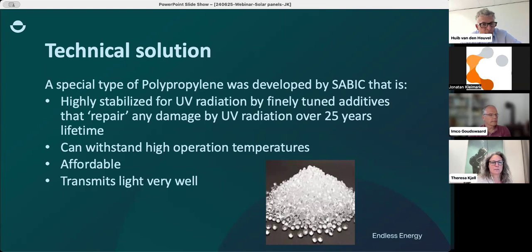So it can be used at quite a high temperature range. In our climate tests, we test them from -40 to 100 degrees. High UV radiation, impact, it's very good at impact, and it's completely non-corrosive. So for example, in salty water or with other aggressive environments, it's completely not attacked. Also, like Imco said, it's very affordable. It's one of the most economic polymers that you can use, and it's also very transparent for light, which is of course extremely important for solar panel application.